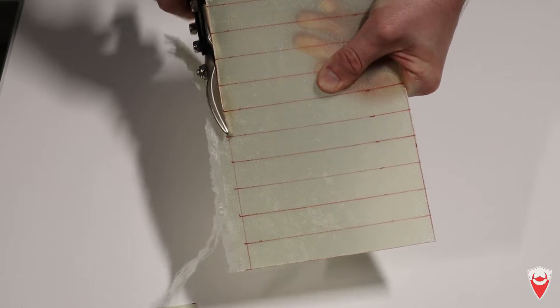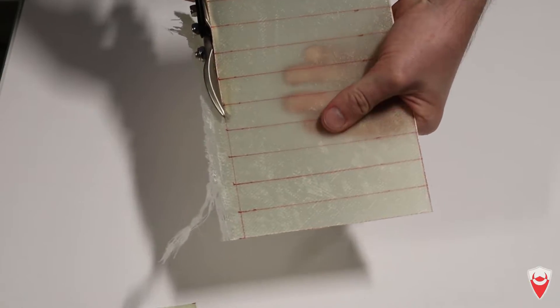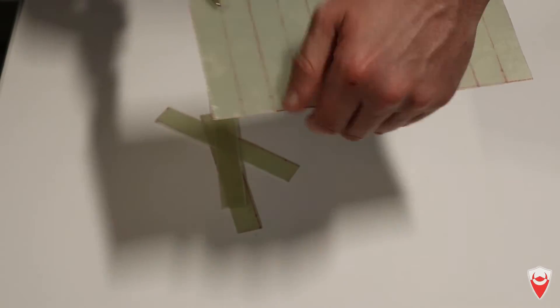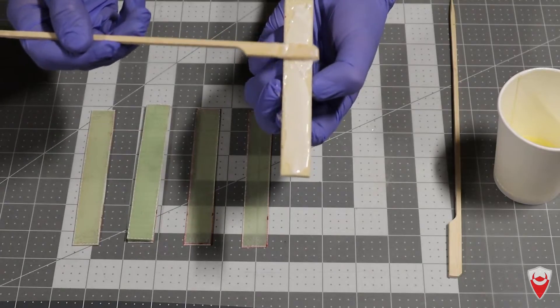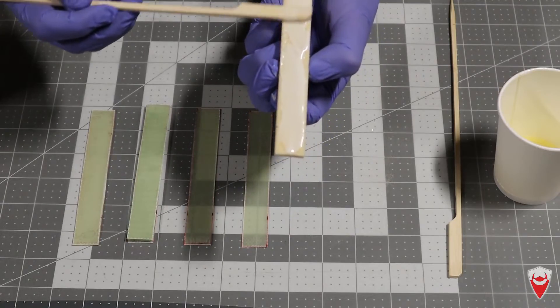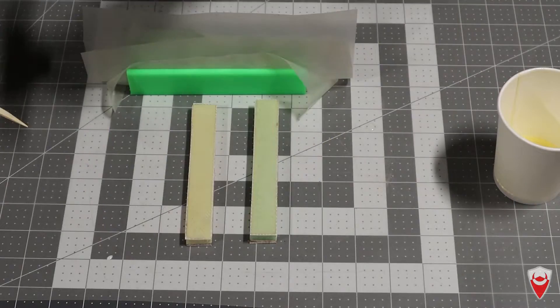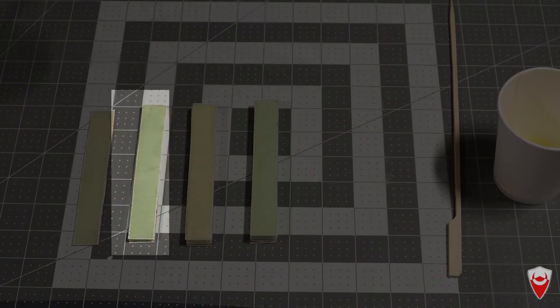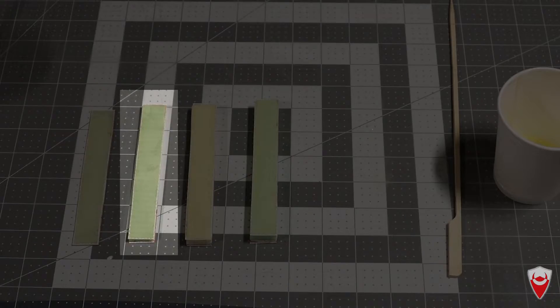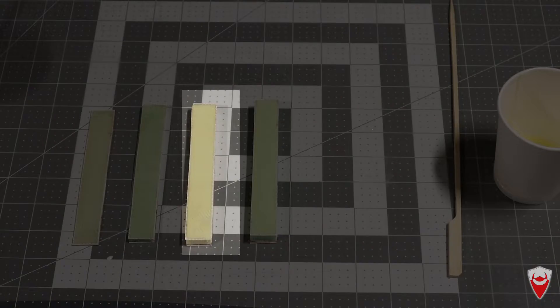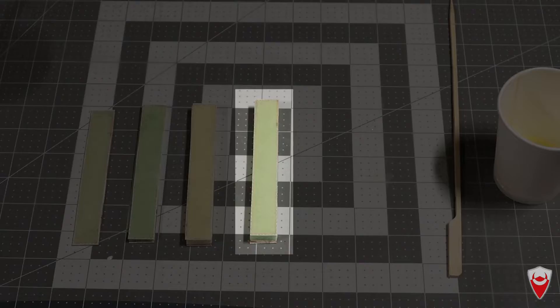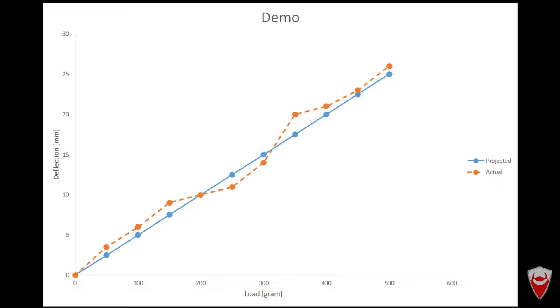Now let's look at the experiment. We're going to take a flat piece of fibre glass with a known layup — two layers at 0/90 — and chop it down into sample pieces. We'll then bond them to various thicknesses of foam using a glass microbead slurry and clamp it all to cure. The samples are: a double skin; a 3mm PVC foam at 75 kg/m³; a 7mm polyurethane foam at 75 kg/m³; and a 10mm polyurethane foam at 35 kg/m³. We'll load each sample with weight and compare projected stiffness to actual stiffness.